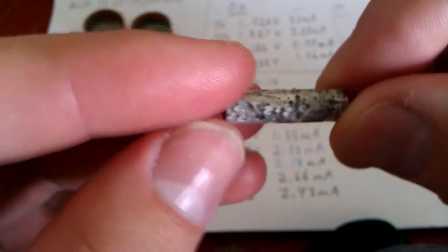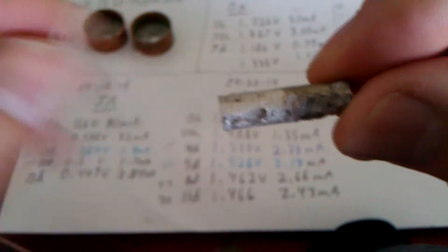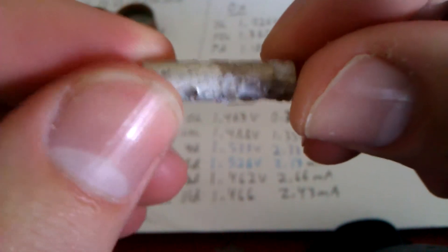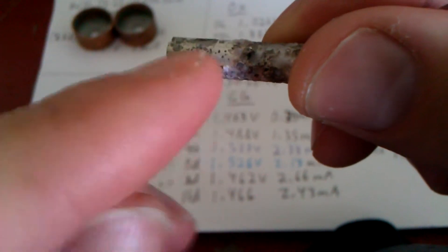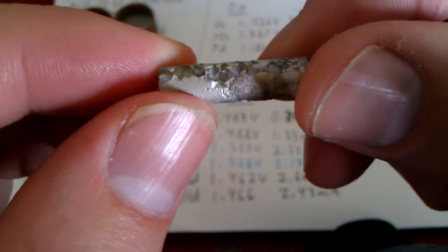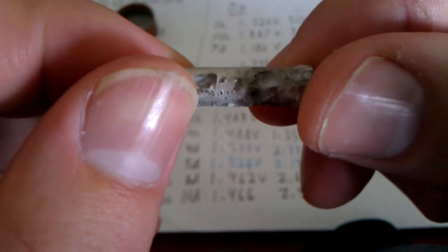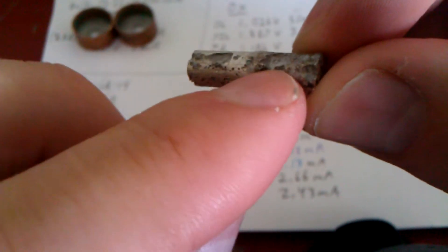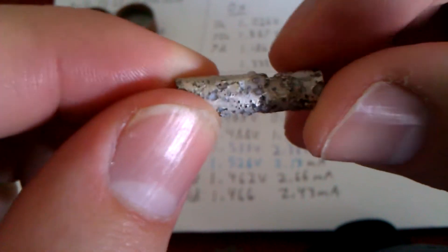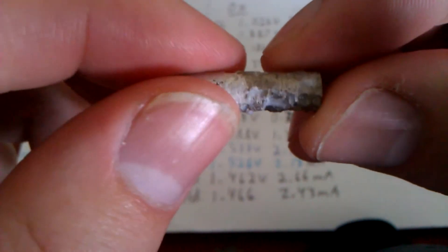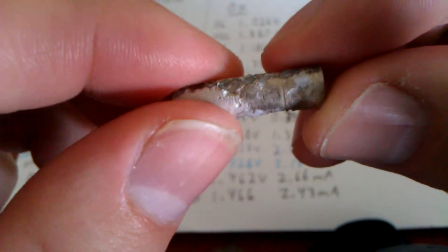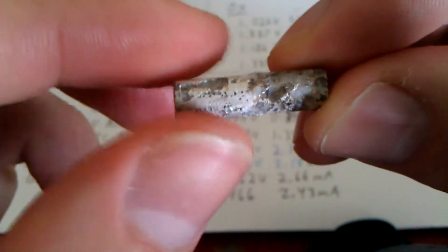And this is the clean oxidization cell. And that is after, oh, 11 days, this is the amount of corrosion. And this cell was already corroded beforehand. So some of this is left over from before. So just a little bit of pitting and just a bit of chew marks. This here, it was really hard to try and get the crystal composition out of all these little cracks and crevices. It was cemented in there pretty good. But yeah, that's amazing. That's almost no corrosion for the amount of time that it was put together.